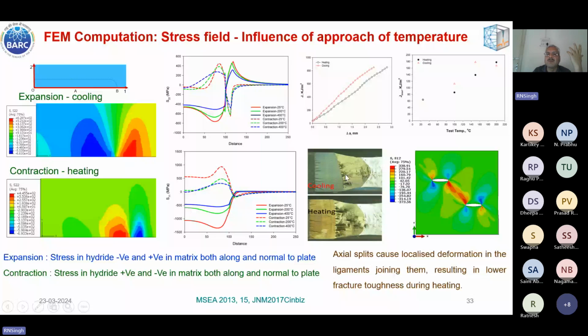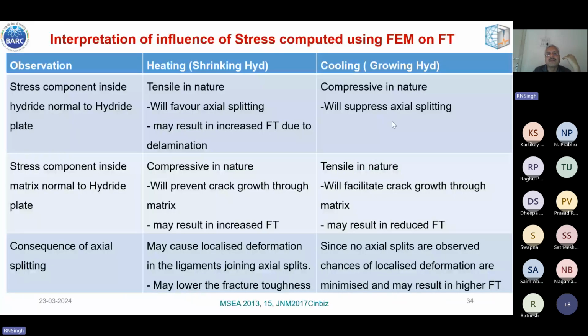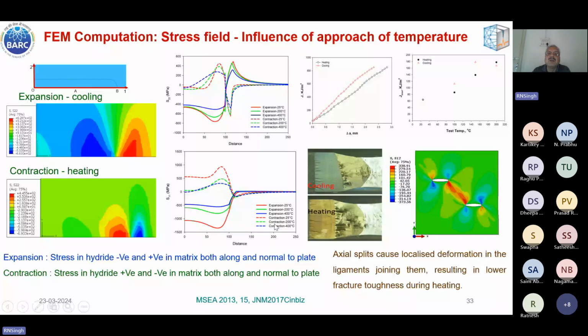So what we propose is that suppose there is axial split, then first axial split takes place, and then deformation gets localized in the ligament joining these two axial splits, and that results in the lowering of the fracture toughness. So in order to summarize, I remember that Arthur Motta's group from Pennsylvania State University, they used our stress values to calculate the lattice parameter of hydride at same temperature by attaining the temperature by both heating and cooling. And they did find that hydride lattice parameter changes depending on the direction of approach of temperature.